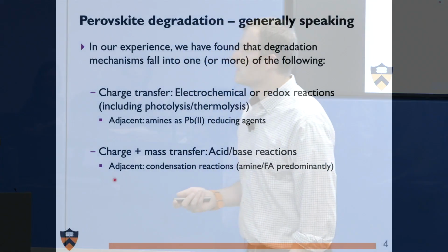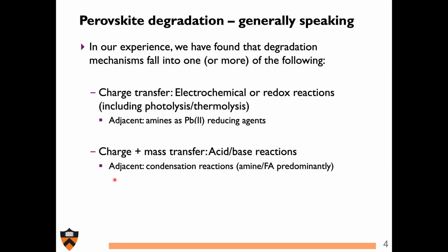And so when we talk about degradation, in my lab, we've looked at a bunch of different degradation reactions, and what we found is that the initiation, that first step, always falls into one of these 2 bins. First one being charge transfer, and I put this in order of importance, so this is the first important one. The most important reaction that underscores the degradation of these systems is some kind of electrochemical or charge transfer reaction. And that's the one that I'll spend most of my time here talking to you about.